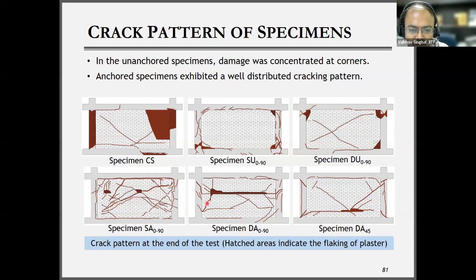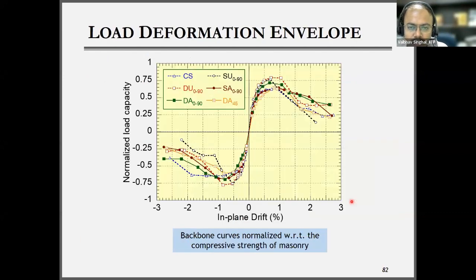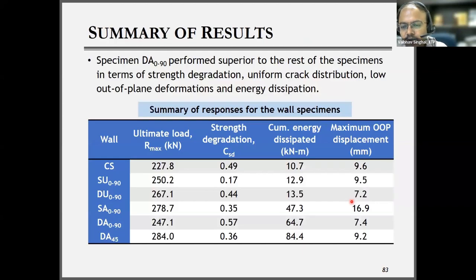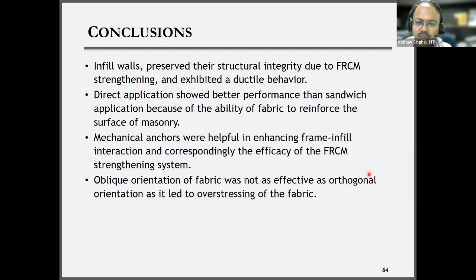Both the anchored specimens have given a better performance, better distribution of cracks or failure in the wall and also in the frame. And similarly the anchored one where the fabric is at 45 degrees has also shown better response. So this is the comparison of all the specimens. The strength improvement is not so significant, but most of the improvement we have seen is in the out of plane response. The out of plane displacement has been much lower when you apply adequate strengthening, and especially with the anchors.